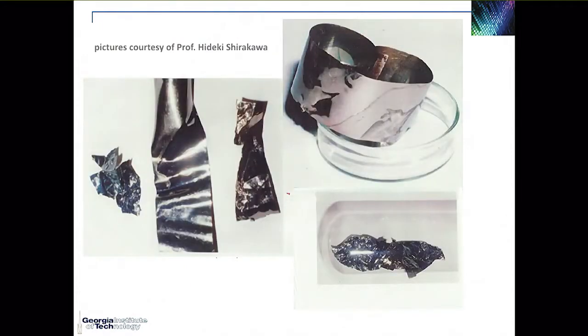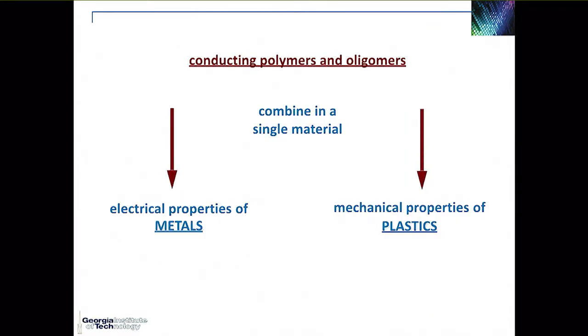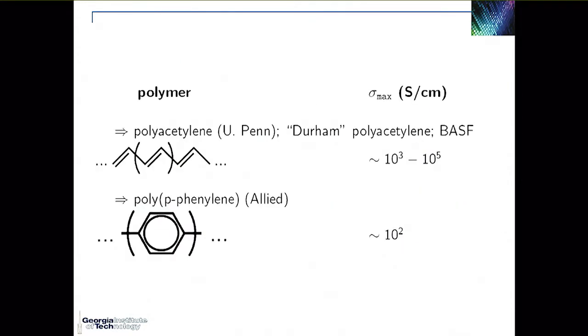And this discovery on these silvery-looking or aluminum-looking films of trans-polyacetylene, of course, triggered a lot of interest in the field, because that was the first time that people saw the potential of combining in a single material, on the one hand, the electrical properties of metals, on the other hand, the mechanical properties that are typical of plastics. So much effort was put into, first, optimizing the synthesis of trans-polyacetylene, especially with Jim Feast at Durham and Herbert Naarmann at BASF, and with electrical conductivities in the best highly ordered polyacetylene thin films reaching 10 to the 5th Siemens per centimeter, nearly the electrical conductivity of single crystalline copper.